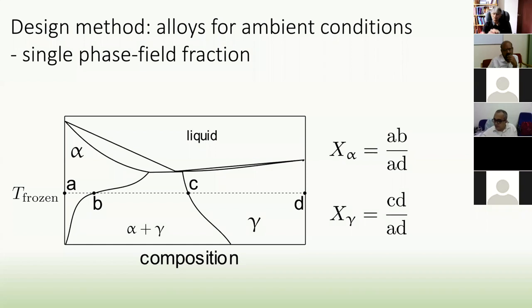Okay, so in the same machine learning method, they wanted to estimate the single phase field fraction for a multi-component alloy. So they designed another parameter where they took, again, the binaries. And you know the single phase extends between A and B and between C and D. So you define these parameters, that the alpha single phase field is AB divided by AD, and the gamma phase field is CD divided by AD.